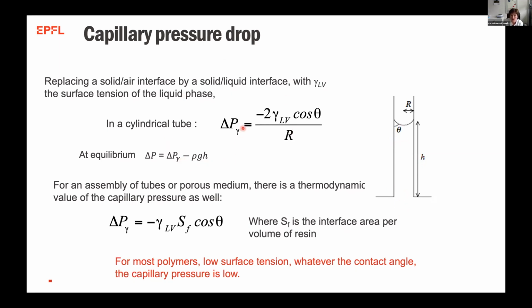And this capillary pressure is expressed as a function of the surface tension of the liquid, cosine theta, this angle that you have here, and r, which is the radius of the tube. So the thinner the tube, when it wets, the higher the capillary pressure you get, which makes sense. That's why we have paper tissue and so on. Now if you have an assembly of tubes or a porous medium, there is an equivalent delta P gamma that can be found, again with gamma LV, the cosine theta, and this time SF, which is the interface area per volume of resin. So it's equivalent to a 1 over R in terms of dimension. It's a quantity of available interface per volume of resin.